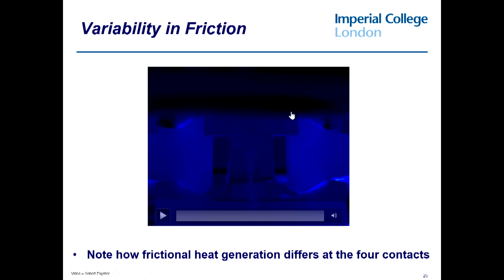Well, what we've got here are four contacts, 1, 2, 3, and 4. You'll see them a bit more clearly in a moment. This is an experiment where we're vibrating these blades and measuring the temperature, so in effect we're measuring heat generation. Now what you'll see is that this contact here is hardly doing anything. So that's got high friction and it's not slipping. This one down here is generating a lot of heat, and that's got low friction and it's slipping a lot.